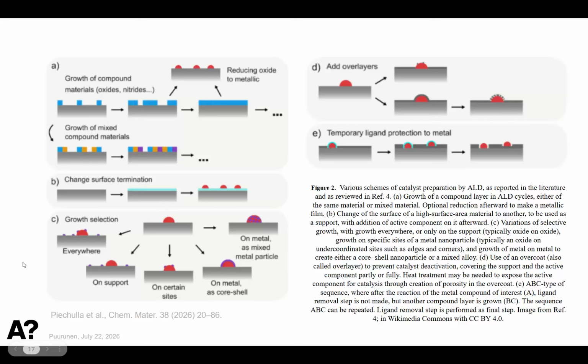You can also play around with selective growth, and this is probably something that's going to become more important in the future. So depending on your process, if you have already a metal on a support, you may add materials either so that they go everywhere, or you might have selective growth on the support, you might have selective growth on the metal or even some certain sites on the metal, or you might be able to grow these core shell particles, but depending on the process, you might also end up having mixed metal particles.